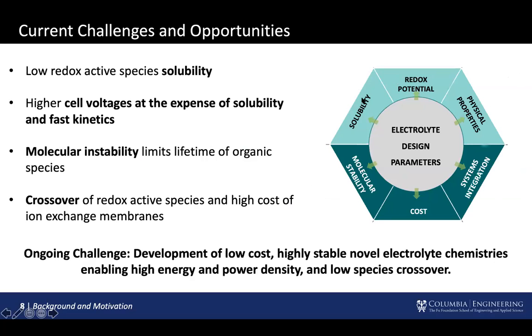I just talked about solubility and redox potential. I talked previously about organics being low-cost molecules, but also being molecularly unstable. We saw that we can increase the efficiency of the system by having ion exchange membranes, but those are very costly. So there are all these different trade-offs that we see in existing flow battery chemistry. There's an ongoing challenge to develop low-cost, highly stable new electrolyte chemistries that enable high energy and power density, as well as low species crossover.